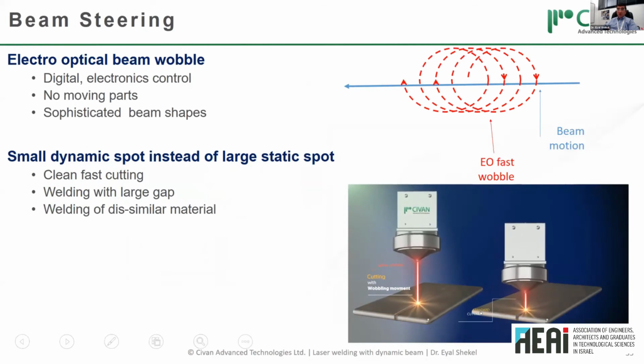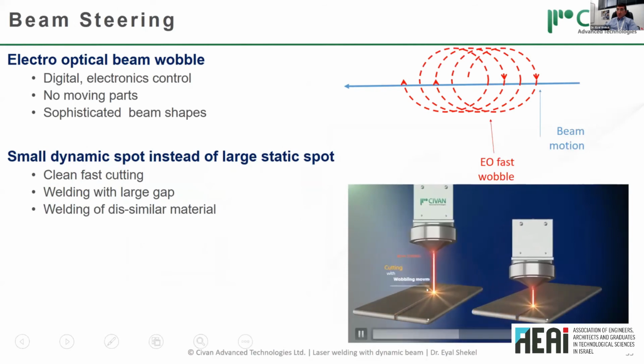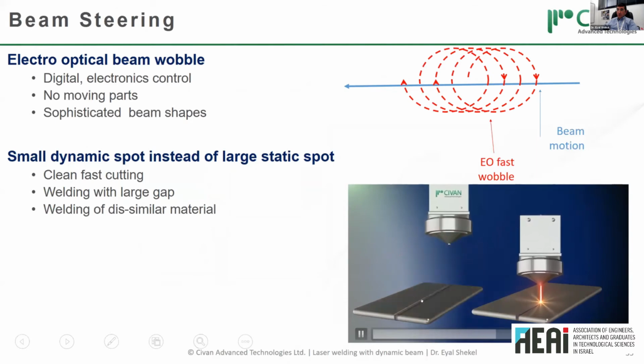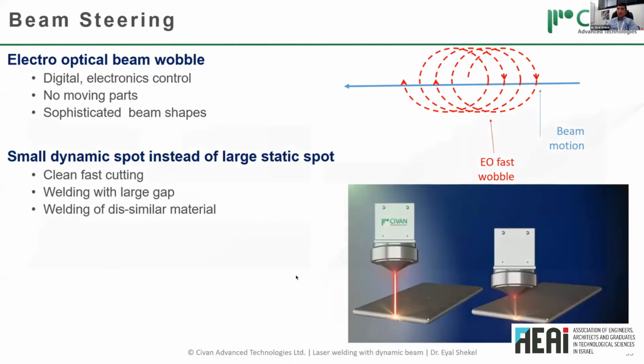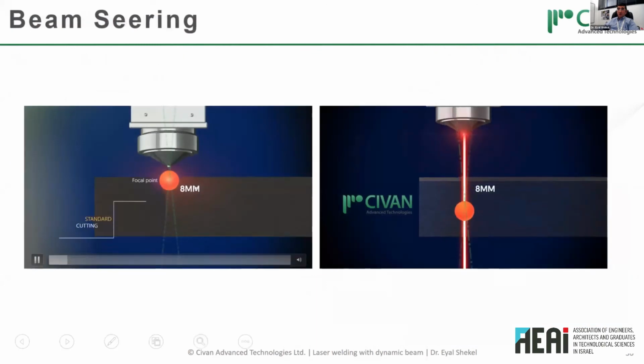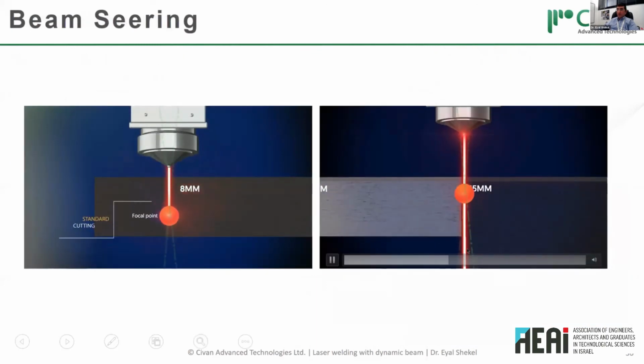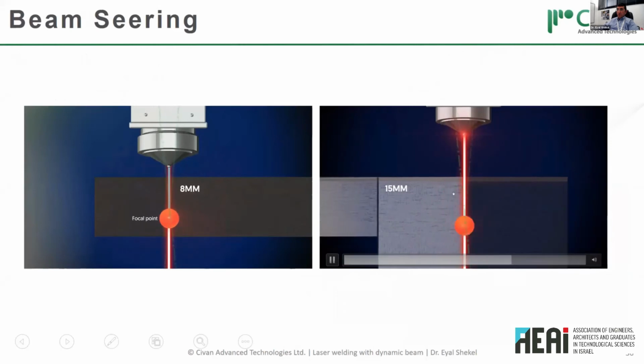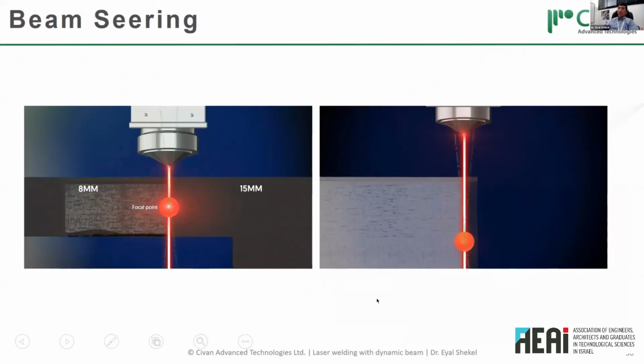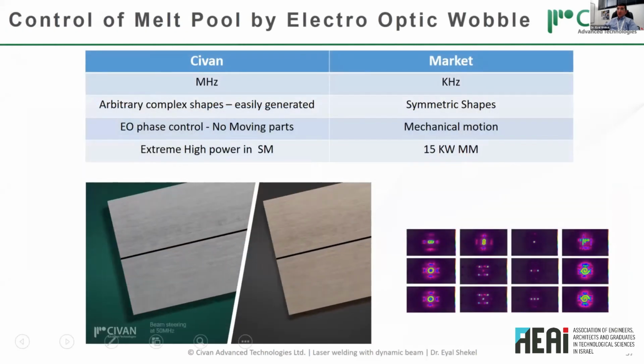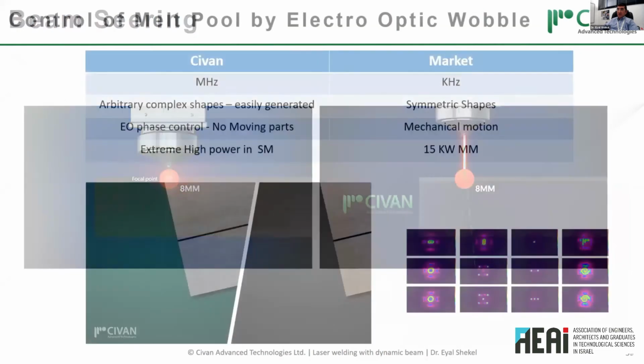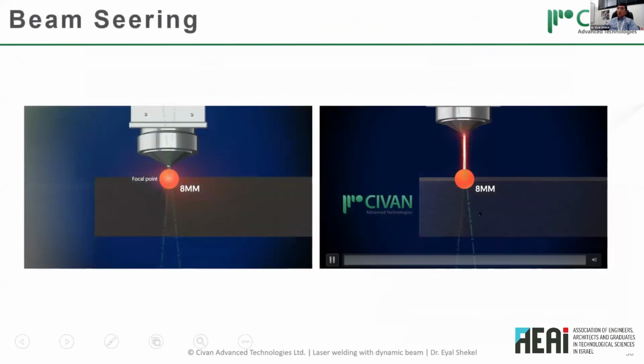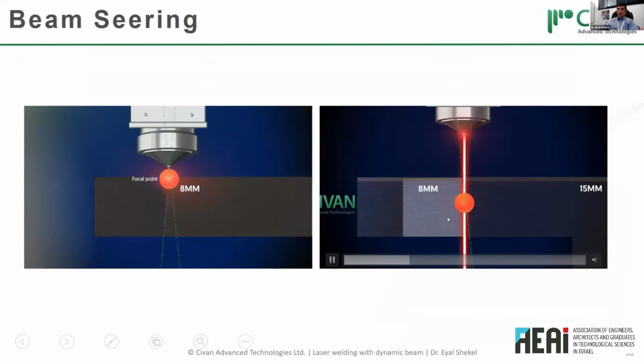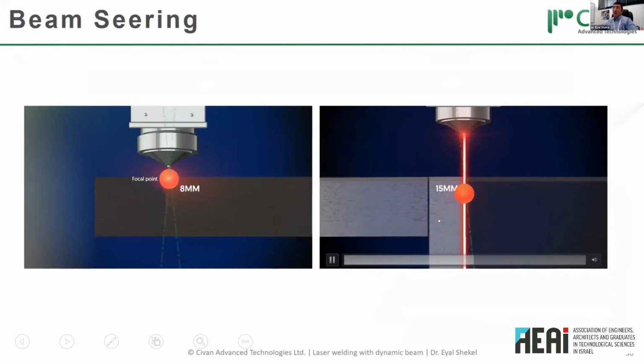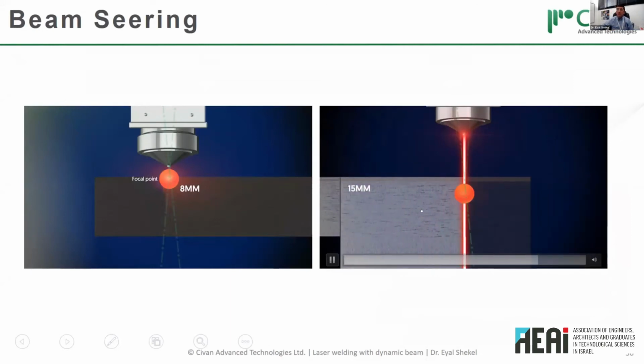So this all gives us the ability to control the melt pool by controlling the beam shape and beam position. We can control the depth of the focal point. And basically, by doing this all together, we can control the position and shape to get full control of the melt pool.